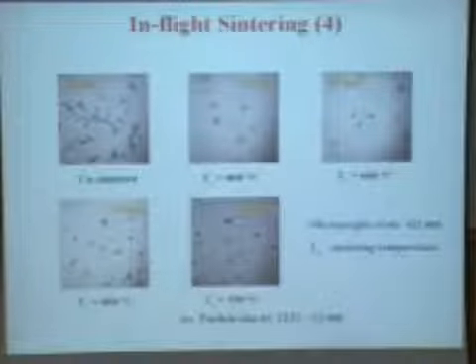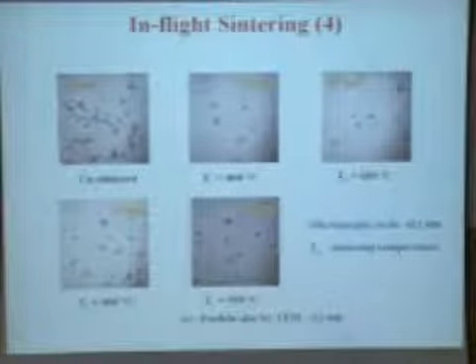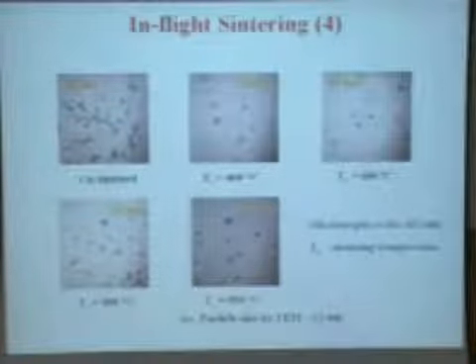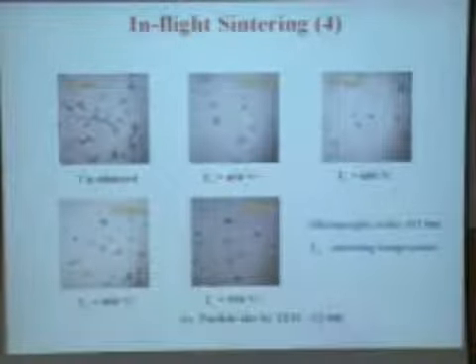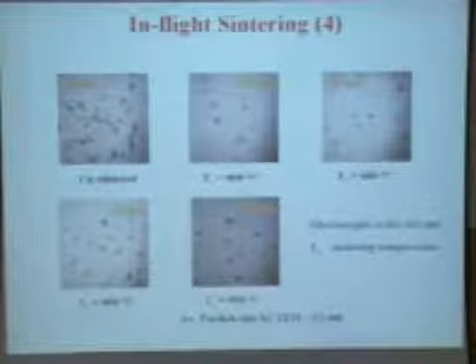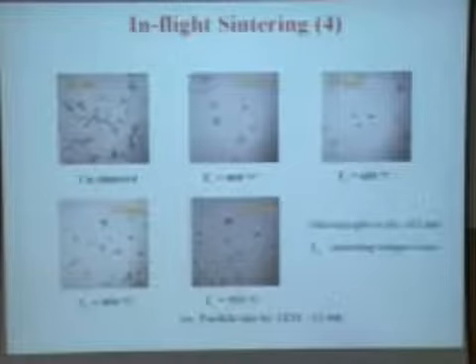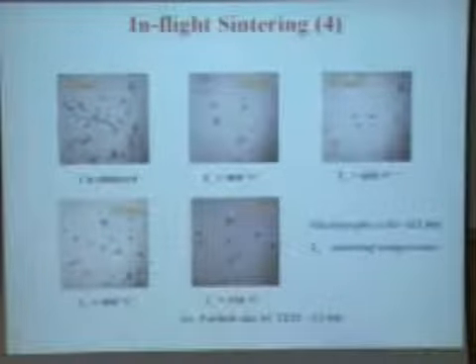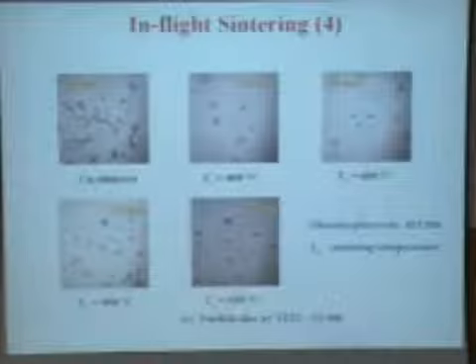If we look at this in the transmission electron microscope, this is what is happening. These were the agglomerates of different sizes and different shapes. They are taken through the sintering furnace at different temperatures. You can see that at 400 degrees centigrade, the compaction has already started taking place. The particles which have a loose structure and arbitrary shape, because they melt, start coming together. The process of compaction starts. After the compaction has taken place, if you increase the temperature further, they will melt and form bigger spherical particles.